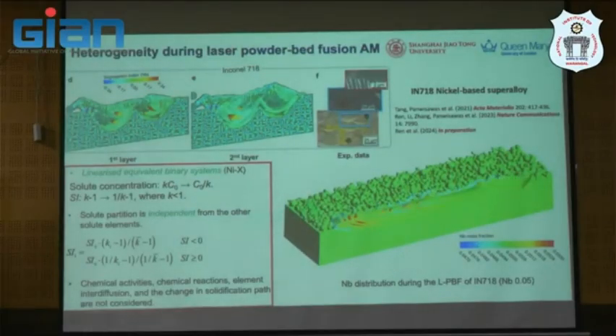So what we do first, we ran a model to understand, this is the real simulation in 718. I will tell you later that we calibrate against small scale, micro or nano length scale experiments as well. So we calibrate this before we predict the solute segregation profile. Especially for Inconel 718, we chose the niobium segregation profile because this is a detrimental phase that's present. I don't need to repeat this, it is in the very first slide. And then you will see that we can predict niobium distribution in Inconel 718 here. And it's real that it happens at the boundary, but we don't quite understand it yet. This is just quite a big scale model.